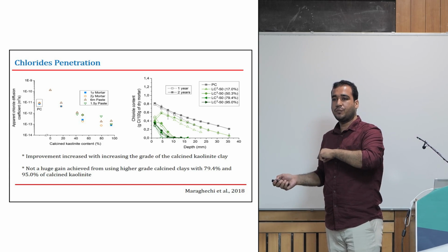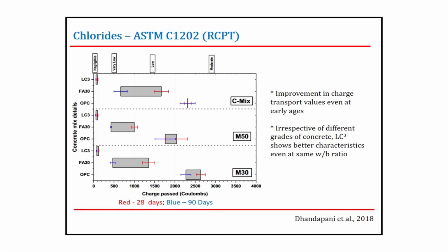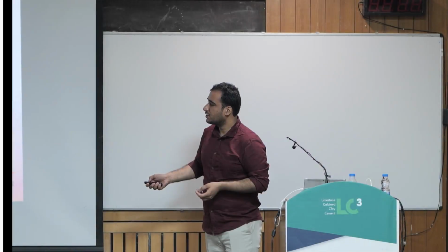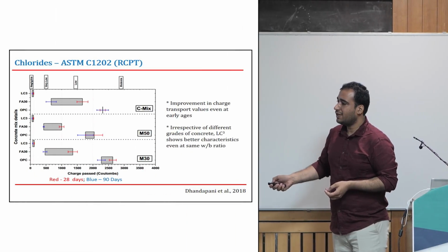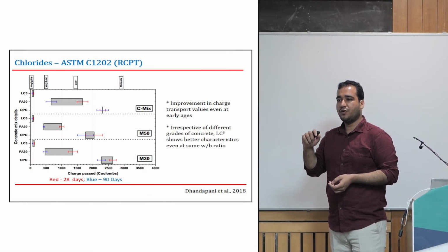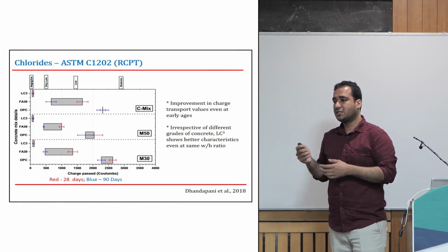It's much better compared to the OPC system here. To show you more results, these are the charge transport values comparison of OPC, PPC and LC3. You can see that LC3 charge transport is almost in the negligible range for all the mixes compared to OPC, PPC. In fact, even at 28 days, yesterday we talked about the pore refinement in Professor Srijit's lecture, right?